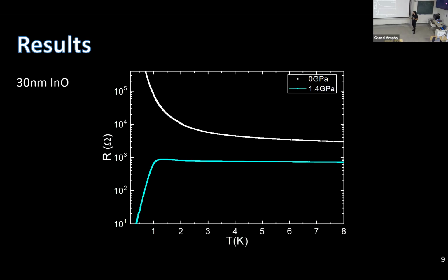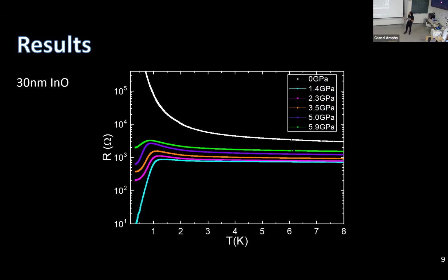We see the superconductor-to-insulator transition. We see the transition from an insulating sample to a superconducting one. And we see that we undergo the transition for the first time under pressure. I say first time because as we continue increasing the pressure even more, we start to see a destruction of the superconductivity. As we continue increasing the pressure, the critical temperature starts to decrease, up to a point where we cross the SIT once again.